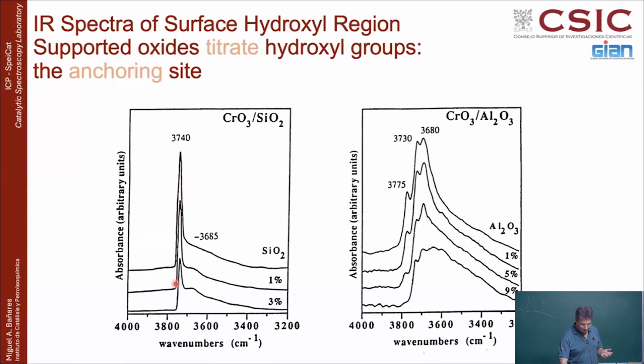If you put 1 or 3% of chromium, the intensity of these hydroxyl groups will decrease because some of these hydroxyl groups are taken by the chromium to make silicon-oxygen-chromium bonds. And then basically you can see how many of these surface hydroxyl groups are taken, what is the degree of coverage of chromium in this case on silica. On silica it is very easy because there's only one site, so you will see it linearly decrease until there are no more hydroxyl groups. Basically that will be the monolayer. So you cannot disperse anymore because there is no more anchoring site.